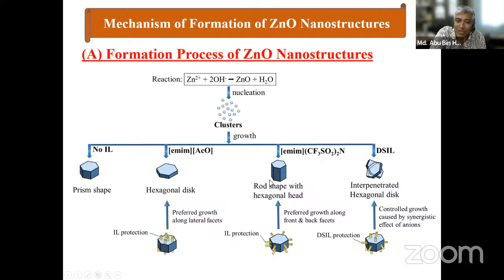When we have the bis(trifluoromethanesulfonyl)imide anion, you can see that this direction is not controlled. This is becoming rod shaped. That means the control is now in this direction. So this cannot become thicker, but this can become rod shaped. But if we have double salt ionic liquid, that means we have control from this direction as well as from the vertical direction. So controlled growth is caused by the synergistic effect of anions. Two anions collectively, cumulatively affect the growth structure. So we have interpenetrated hexagonal discs as we have seen in the TEM and SEM images.